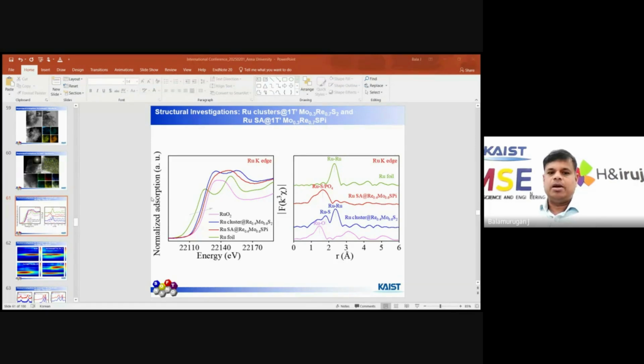But when we go for the ruthenium single atom, compared to the cluster, the ruthenium single atom may have around 1.5 or 2 oxidation states. It may be between 1 and 2, so we call it maybe 1.5 oxidation state. So from these studies, we conclude that ruthenium is present as single atoms, and we also see in the cluster a few ruthenium-sulfur bonds and the remaining ruthenium-ruthenium bonding, and that bonding is called a cluster. But when transformed to the single atom, there is no peak observed after 2 R values. Then we confirm that our material is 100% transformed from cluster to single atom.